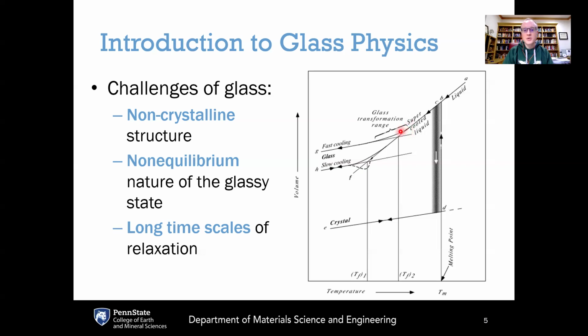When that happens, we get a departure from this metastable equilibrium, and this corresponds to a gradual freezing in of the structure of the supercooled liquid. So the structure is gradually becoming frozen in into a solid-like but still disordered state. And that resulting material is what we know and love as a glass. So a glass has some properties that are like a solid because the atomic positions are more or less frozen in. It behaves mechanically a lot like a solid, but it has the structure of a liquid because the structure of the glass is just the disordered structure of the liquid that becomes frozen in.